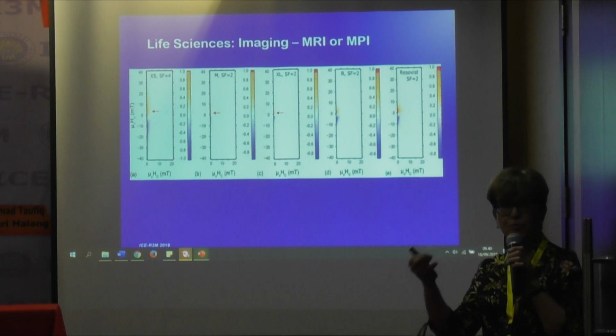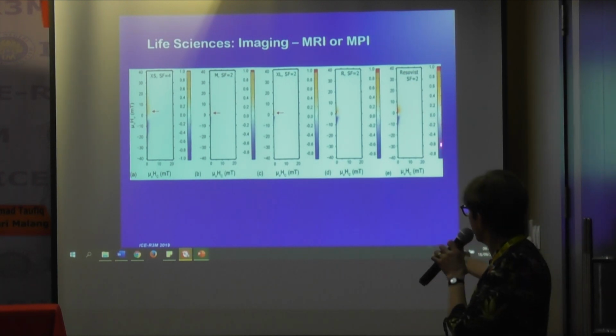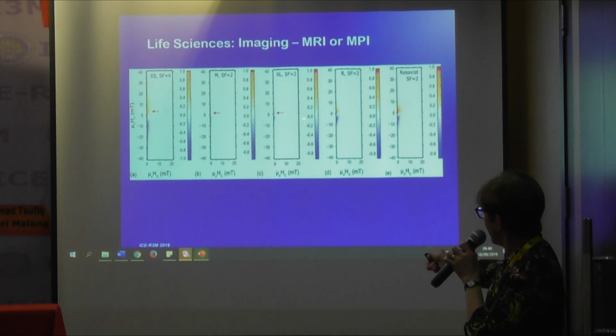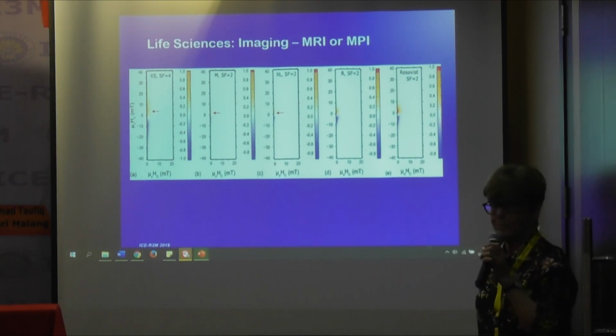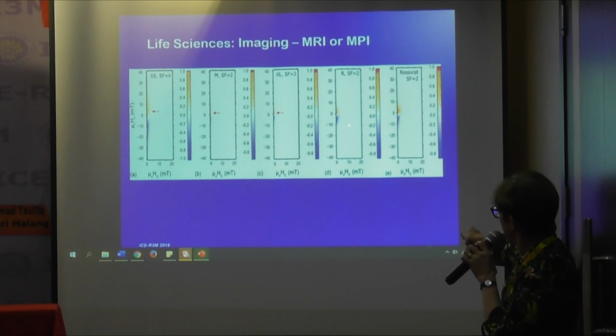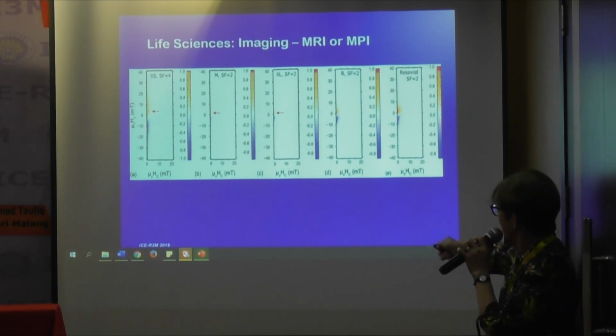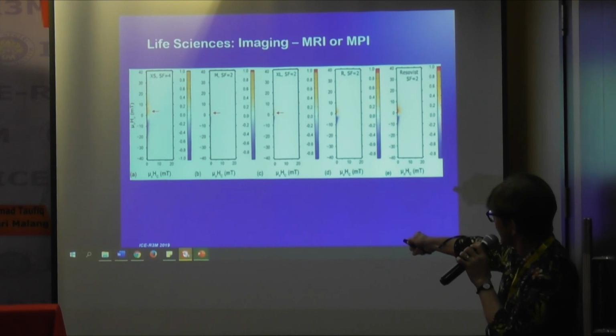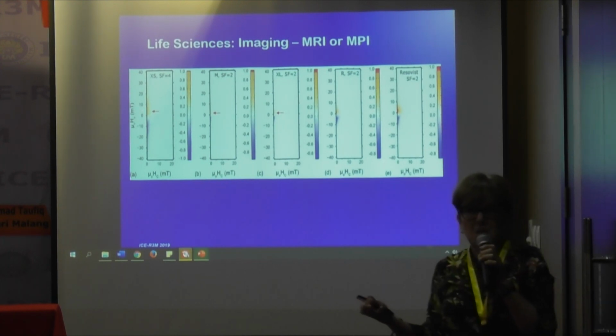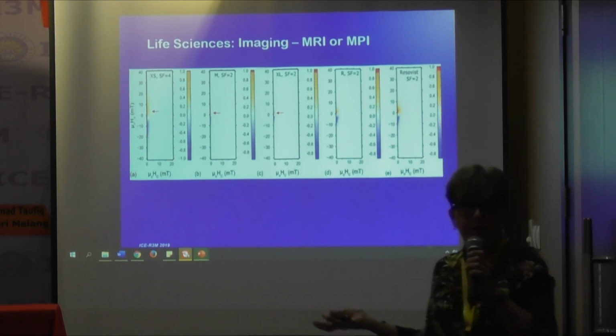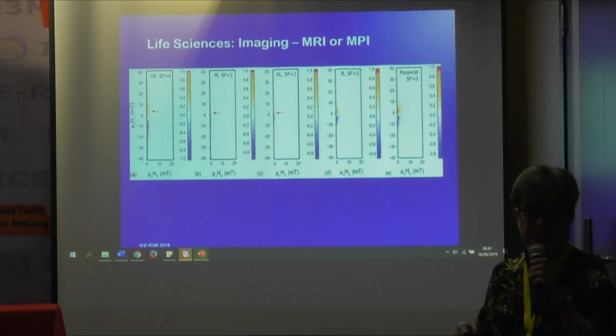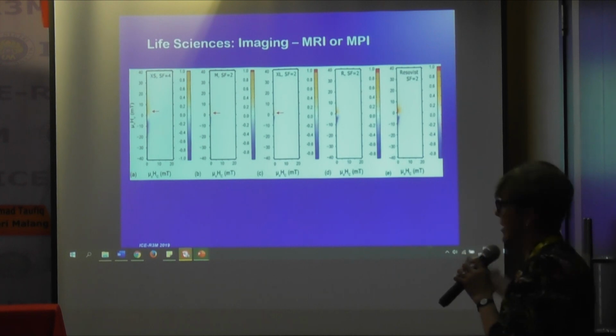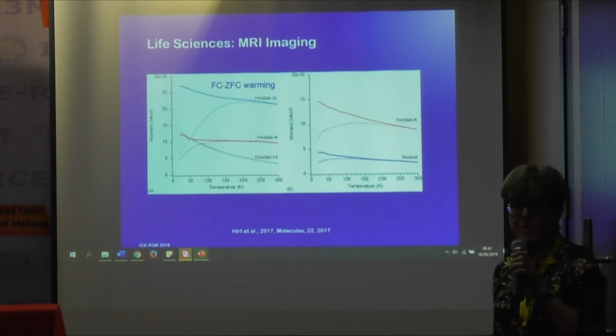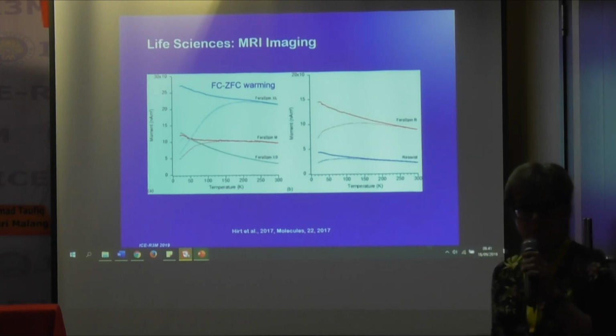So first we thought, okay, if we wanted to distinguish these to try to decide which one would be the best for predicting performance, we first looked at FORC diagrams. Because they're superparamagnetic, in the FORC diagram everything's at the origin. But one thing you can see, for the R, it's all shifted up above the zero, the main point, which shows it's superparamagnetic. The finer the grain size, the higher the shift up above zero. But in practice, this wasn't very diagnostic for saying how well the product would perform. So next. Then we tried another method, and this is called field-cooled zero field cool.